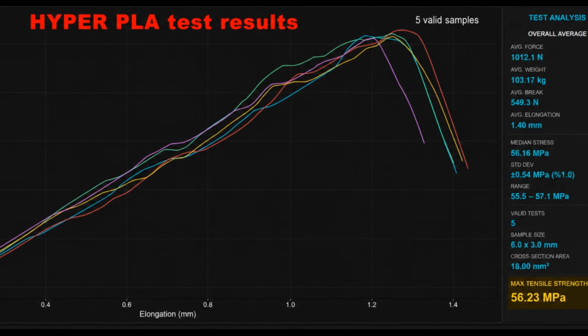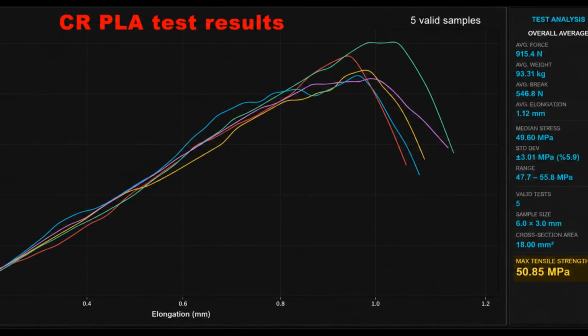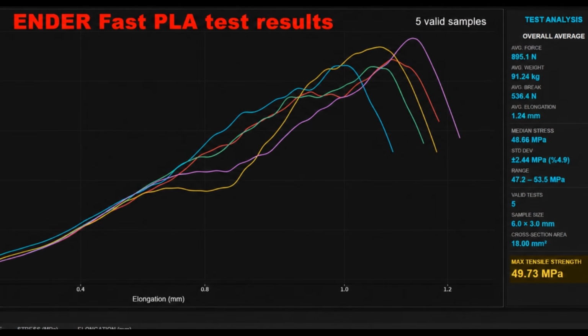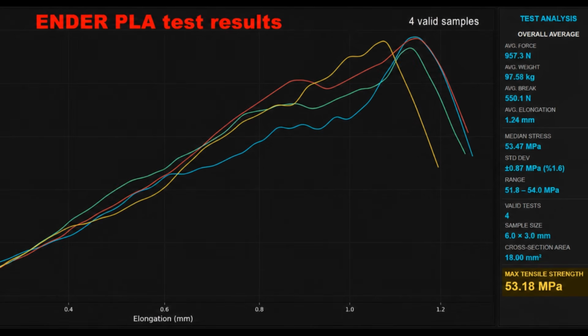Creality Hyper PLA reached a pretty decent value of 56.23 megapascals, and during this test the material stretched by 1.4 millimeters. The tensile strength of Creality CR PLA is 50.85 megapascals, while its elongation value is 1.12 millimeters. When we move on to Enderfast PLA, the tensile strength is 49.73 megapascals, and the elongation value is 1.24 millimeters. And finally, in the test conducted with Ender PLA, the tensile value is 53.18 megapascals. The elongation value during the test was measured as 1.24 millimeters.